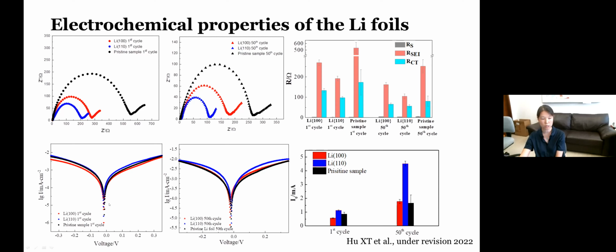Now, for the Tafel test, we see the exchange current density. At the first cycle, there might be a little bit of difference among the three samples. It seems that the lithium-110 is slightly higher than the others, but the difference is not significant until later. At the end of the 50 cycles, you see the exchange current density of the lithium-110 is much higher than the rest, suggesting the lithium plating and stripping is a lot easier to take place on the lithium-110 sample in comparison with the other two.